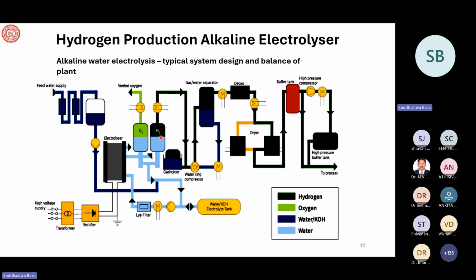from the cathode side and anode side, hydrogen and oxygen go as a gas, and the unreacted water having more hydroxyl, because it is an alkaline electrolyzer, goes down. Makeup water is added, and makeup NaOH or KOH, if they are the electrolyte, is added. Water and KOH electrolyte tank being added, measured, and checked whether they are at the right temperature and pressure, and they are sent to the electrolyzer again.